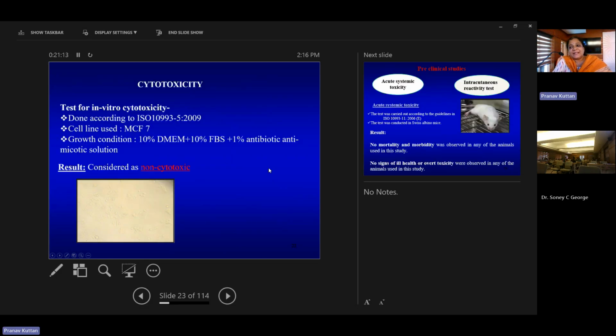Once after optimizing the physiological parameters, next we need to see the biocompatibility, like how this product is going to behave when it is going to be used in the human body. The first test is the cytotoxicity test. Any biomaterial has to be checked for cytotoxicity. We have done it as per the ISO standard, and MCF7 cell lines were used. The image is not very clear actually, but it shows round cells. That means the cells are not damaged when in contact with this hydrogel. So that means it is passing the cytotoxicity.